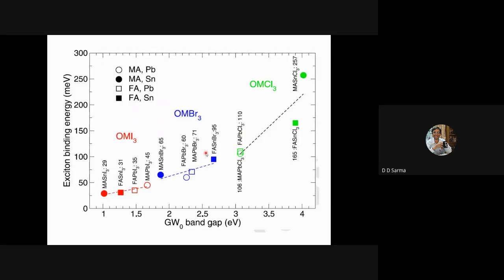We estimated it for several compounds. In fact, in collaboration with the Vienna group earlier, we had estimated from very sophisticated, very large-scale computation what the excitonic binding energies should be for all these materials, plotted as a function of calculated band gap. And we have now estimated from the experiment for FAPbI3, MAPbI3, FAPbBr3, MAPbBr3, as well as some of the cesium compounds. And I'm going to show our estimates. These are the estimates. You can see they compare very well to the MAPbI3 and MAPbBr3 theoretical estimates, showing that now we are getting reliable values.